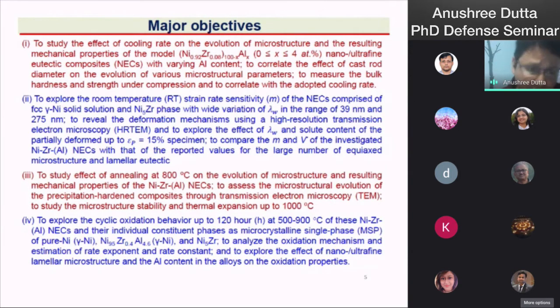And the last one is to explore the effect of cyclic oxidation behavior up to 120-hour oxidation at 500 to 900 degrees centigrade of this nickel zirconium aluminum NCs and their individual constituent phases in the form of microcrystalline single phases of pure nickel, gamma nickel, and Ni5Zr, to analyze the oxidation mechanism, rate exponent, and rate constant, and to explore the effect of nano, ultrafine, lamellar microstructure and aluminum content in the alloy on the oxidation properties.